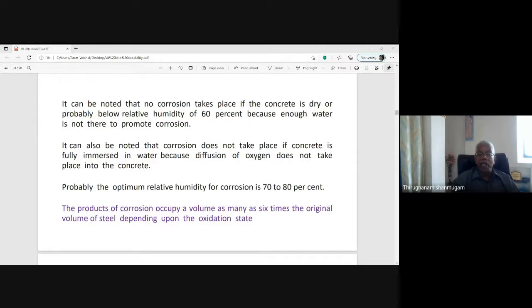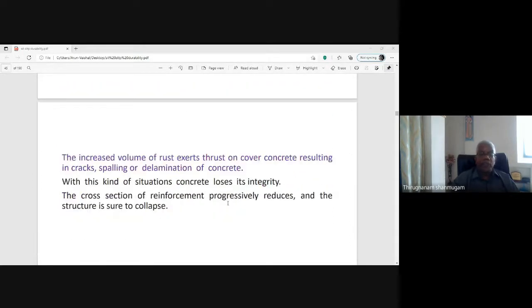So the product of corrosion occupies a volume as much as 6 times the original volume of the steel, depending upon the oxidation state. That is a very important parameter. So you have to arrest the corrosion. The increased volume of rust exerts thrust on the cover concrete, resulting in cracks, spalling, or delamination of concrete. In this situation, concrete loses its integrity and the cross-section of the reinforcement progressively reduces, and the structure is sure to collapse. The cross-section reduces because the diameter is reducing from 12 mm to 8 mm. With an 8 mm rod, it cannot satisfy the load carrying capacity. So the structure fails.